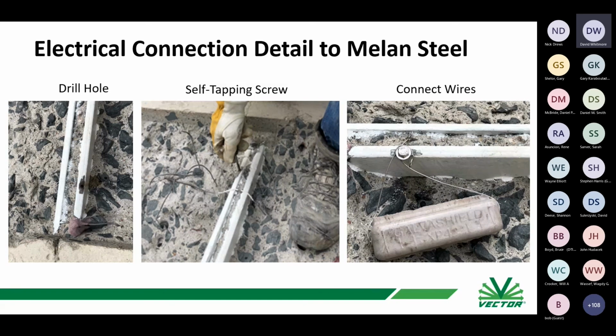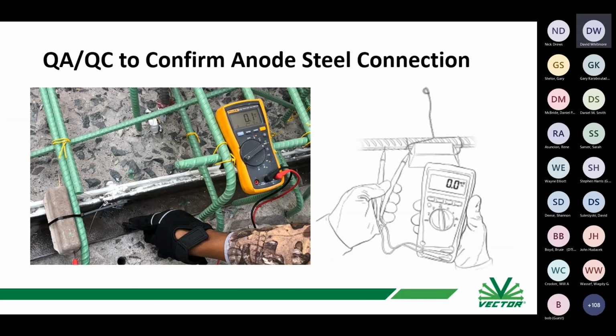So we're actually drilling a small hole into the Melan steel using a self-tapping screw and making an electrical connection that way. And then there's really good QA, QC protocols in the contract, and they're being used on site. So the electrical connections are being checked with a multimeter, and you want to make sure that the resistance in that connection is below a certain threshold. Normally it's less than 1 ohm.